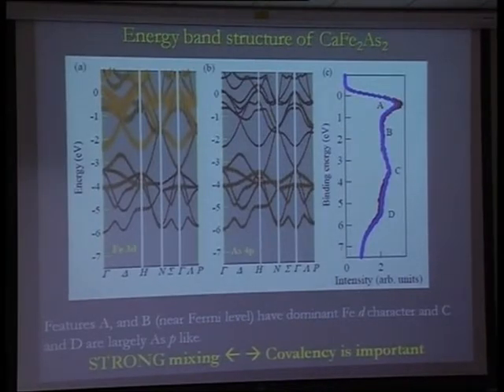Okay, so now let's look at the band structure. This is a simple LDA because the correlation is not so important. So one can directly correlate this band structure to the photoemission spectrum, which has been apparent here. So these are various bands from simple LDA calculations, and the width of these lines represents the iron 3D character here, and here is arsenic 4P character.